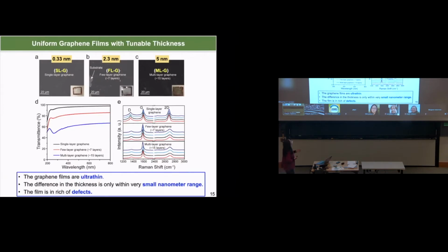So here is the experiment to show that we will be able to achieve a different thickness of the graphene layer. As I mentioned, it can be controlled from just 0.3 nanometer to 5 nanometer, and we give different names. So this is called the single layer graphene film, and the 2.3 is around 7 layers. So this is called a few layer graphene film, and we have this multi-layer, around 15 layer thickness of graphene film. I want to mention that the difference in the thickness you can see is only in a very small nanometer range, and later we find that such a small difference actually makes a really huge electrochemical performance difference in terms of the battery performance.